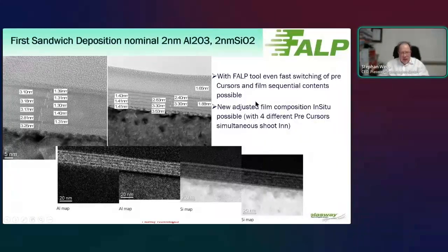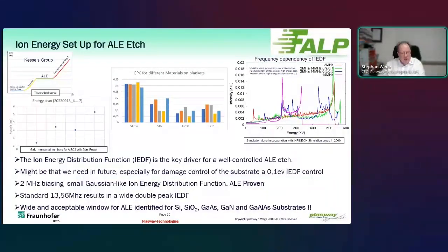With this system, we also can change very fast from one material to the other. Again, this is just possible with our new flow dynamic system, but we can also handle in our system 4 different precursors. So for example, here we can build up a sandwich, 2 nanometer aluminum oxide, 2 nanometer silicon oxide, step by step. And when you make here an XPS analysis, you see also very nicely the different stoichiometry of these different materials. So now we come to the etching.